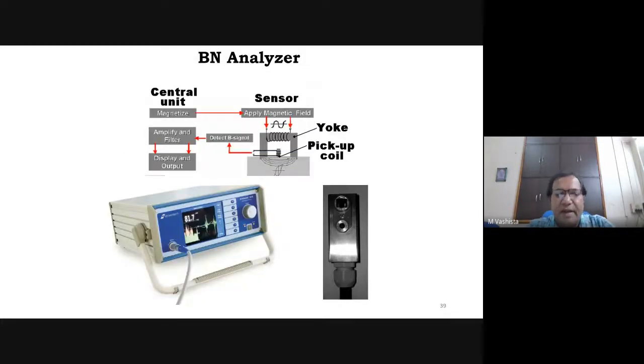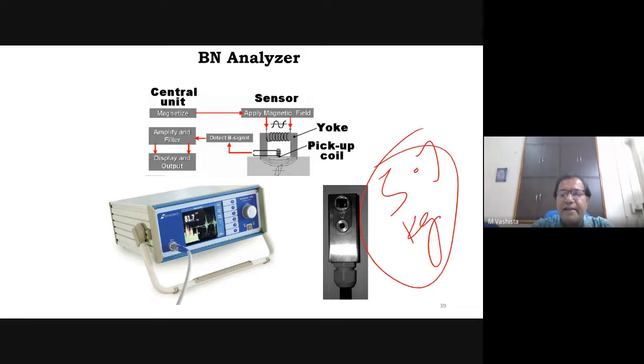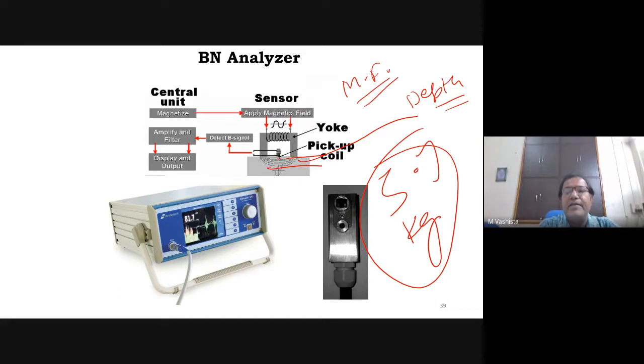This is the actual image of the Barkhausen noise analyzer. This is a portable equipment. Its weight is around 5.7 kg. So I can say it is a portable equipment, and this schematic indicates the depth of penetration, which I can change because the magnetic field is governed by frequency, and the higher the frequency, the lesser the depth. Frequency is inversely proportional to depth. So by changing the frequency of the magnetic field, I can assess the depth. So micro level characterization, macro level characterization can be carried out using this technique.